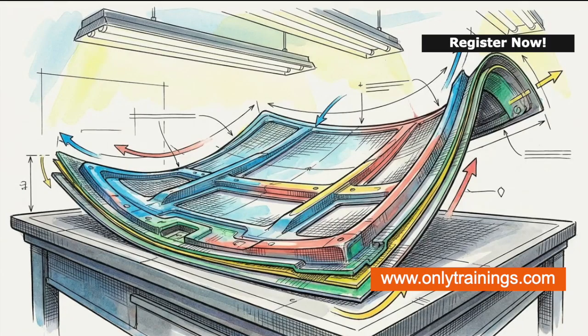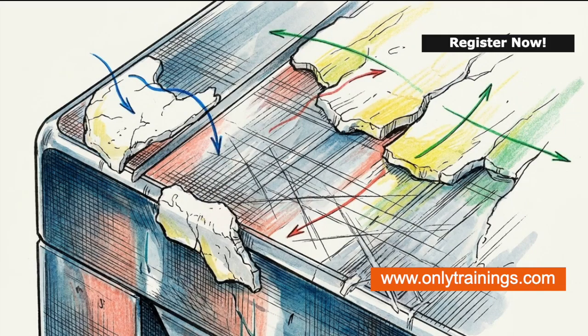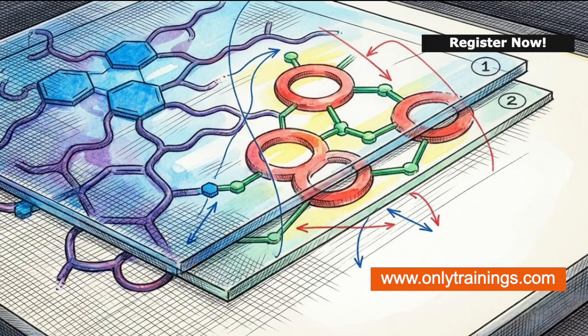This erratic shrinkage pulls on the internal fibers. It physically warps the final part, damages expensive precision molds, and completely deteriorates surface cure in delicate gel coats. Introducing a new reactive monomer requires a customized, highly calibrated cure strategy. The concept of a true drop-in replacement is a myth.